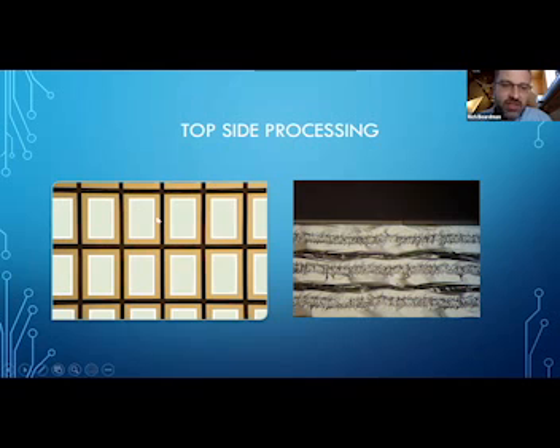So right here, what we have is some images of the top side of a wafer post-stealth. For those of you that have experience with mechanical dicing, you'll notice that on this image that we're showing, you see zero topside chipping here. And it's a true statement to say that stealth can offer almost zero topside and backside chipping. You might see a slight meandering of the beam within 1 to 2 microns, but you're looking at absolutely pristine quality on the surface and backside of the die.